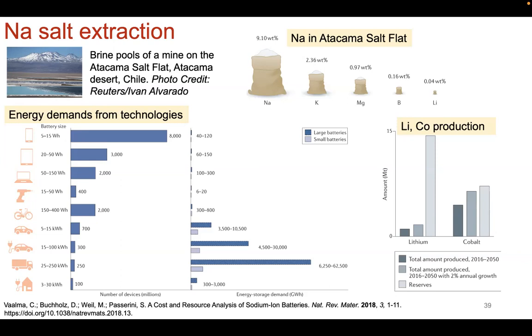producer of these salt vats, these salt brines that the lithium salts are taken from. Now, if we move to, let's say, extraction of sodium salt for the sodium-ion battery electrolyte, we'll see that we can actually get much more sodium salt coming from the same salt flat in Chile, the Atacama salt flat. Now, does that solve our problem of having these huge flats in Chile and the amount of time that it takes to evaporate the water and then purify the salts? No, but you can now get 2 salts from the same location.